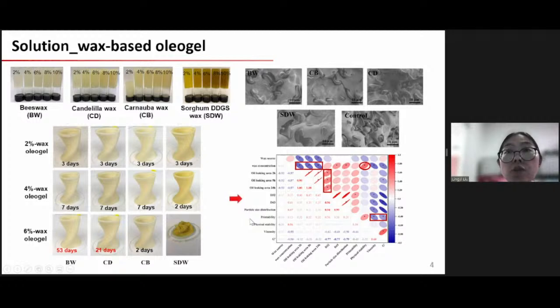For the correlation heat map analysis, we can see the viscosity and the storage modulus were significantly related to the printability. And overall, within the applied wax concentration range in this project, the higher concentration in the oleogel maintained the physical stability better. And also, when the oil leaking area was measured to reflect the oil controlling capacity, we can see this post-printing property was closely related to the wax concentration and the particle size. The smaller particle size can help control the oil leaking area.